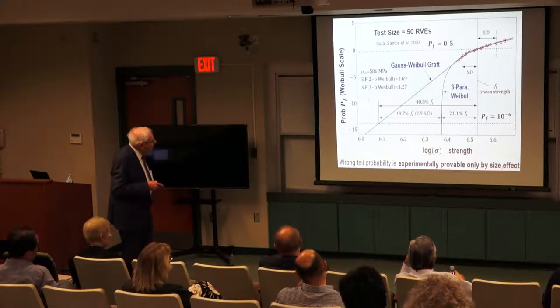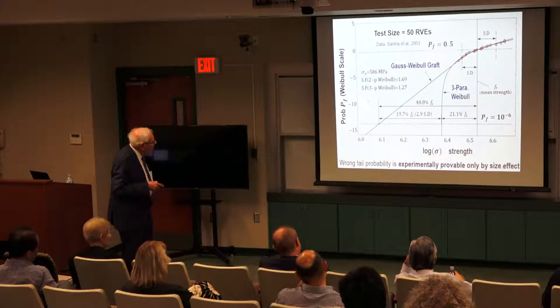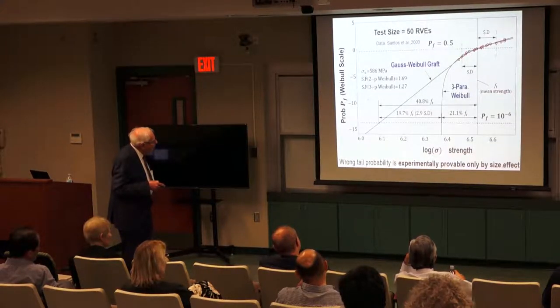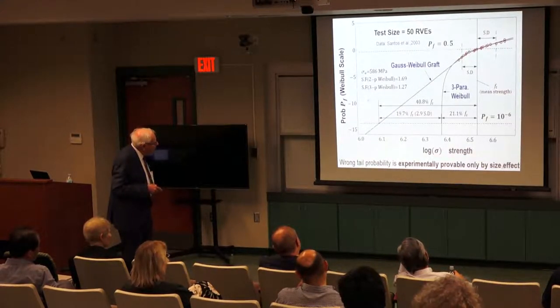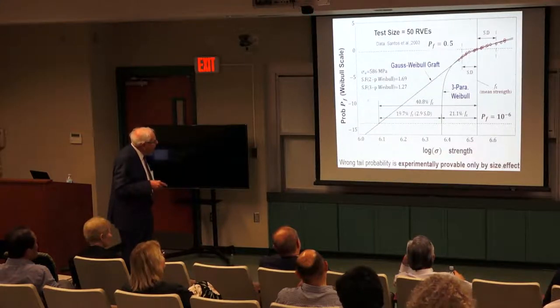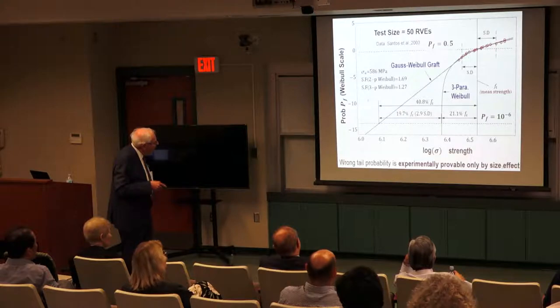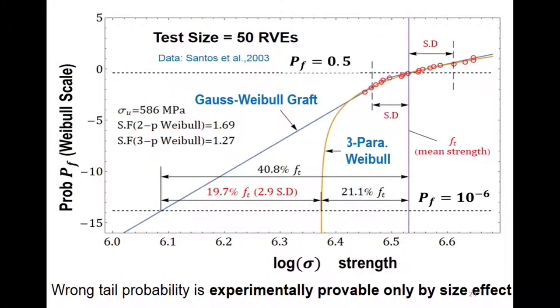These are the data. Of course, some points are aggregates, several points. And this is what is done in most literature. They put a threshold, they have this curve. And then if we extrapolate it our way, with the grafted Gauss-Weibull distribution with the transition, you obtain this diagram.